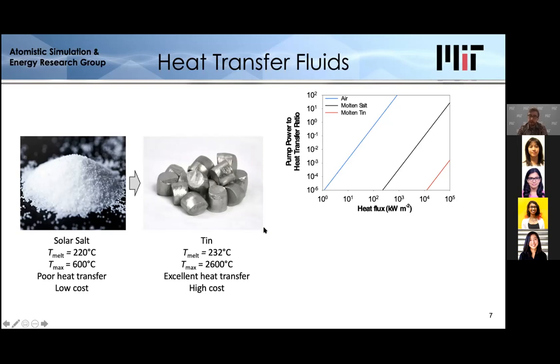If we look across the graph on these lines, by switching from a molten salt to a molten tin heat transfer fluid, we can increase the heat flux by about 2 orders of magnitude, which reduces the area needed for the heat exchanger correspondingly by about 2 orders of magnitude. So that's a huge cost savings that we can get from that.